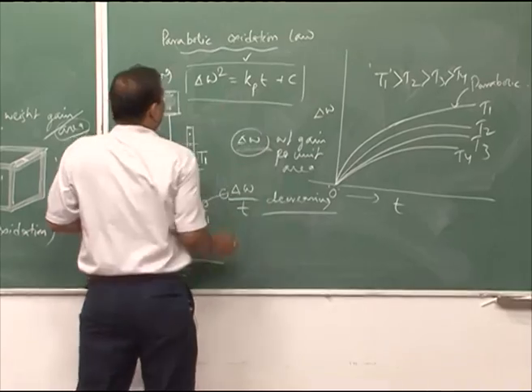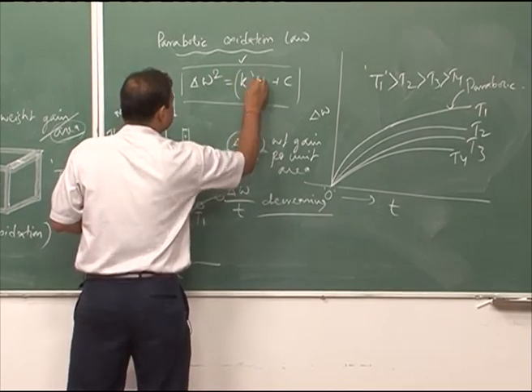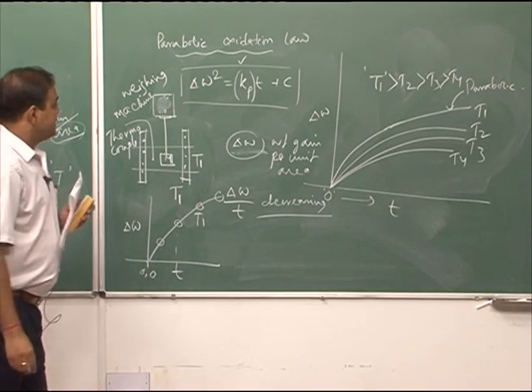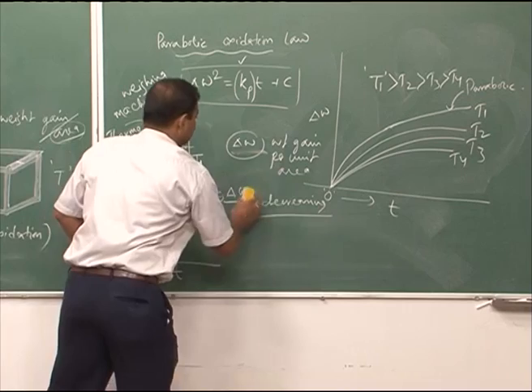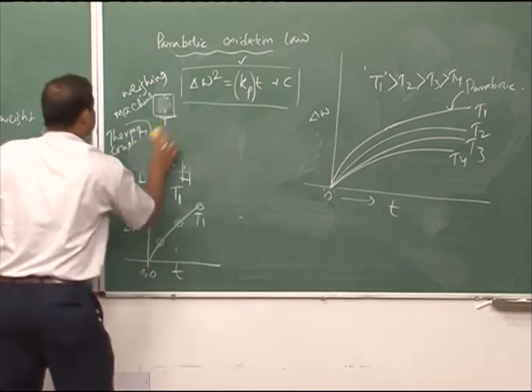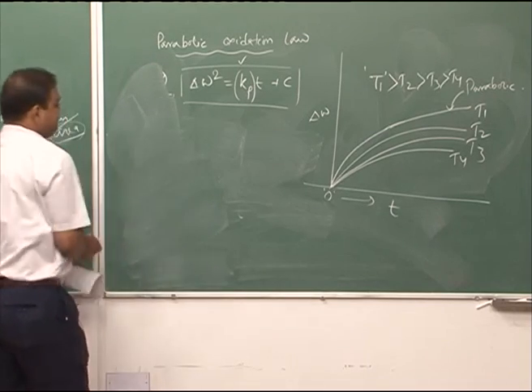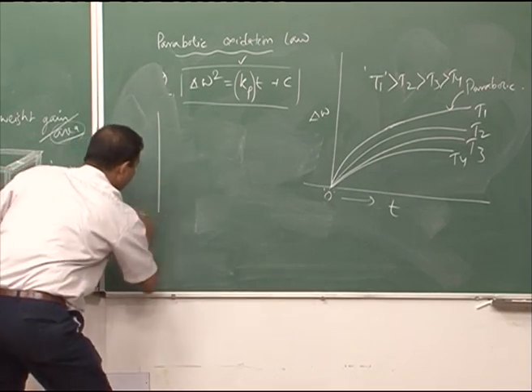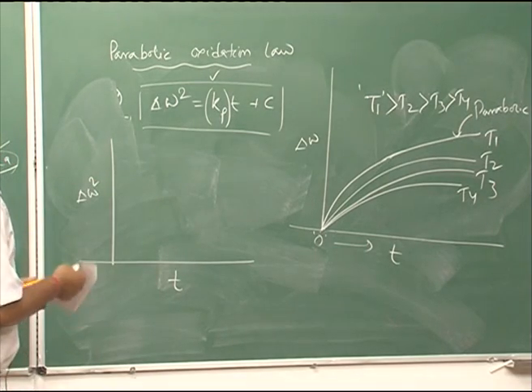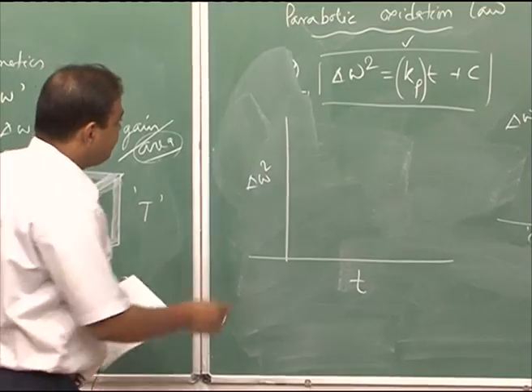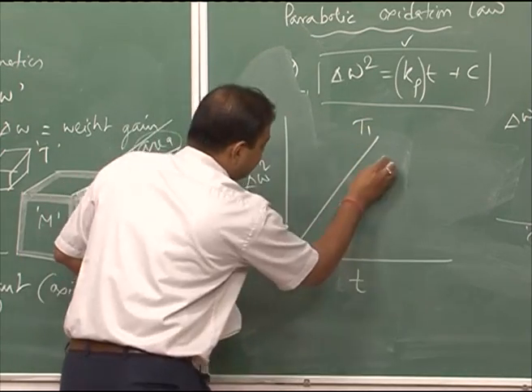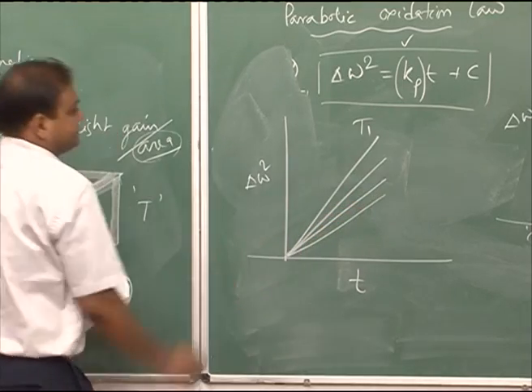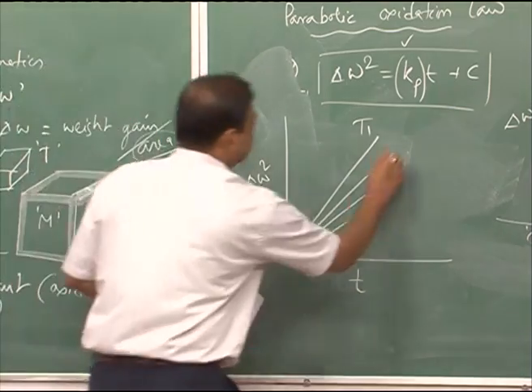Now, from this, what is my rate constant? This is my rate constant, and this P means for the parabolic rate law. Once we have this data, we can calculate the activation energy for that thermally activated oxidation process. Now, from this graph, we can also plot one more graph, which is time as a function of del W square, the weight gain per unit area squared. If it is following a parabolic rate law, then it should give you a straight line for a particular temperature T1. In the second case, it would give a straight line like that.